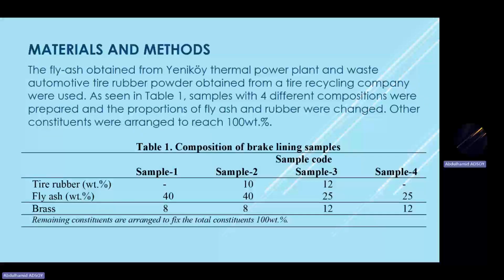As we can see from the table, we manufactured 4 different compositions with different amounts of fly ash and rubber, and the rest of the constituents were arranged to reach a 100% weight for the samples.